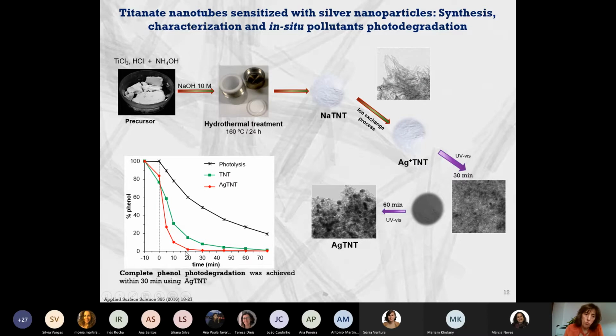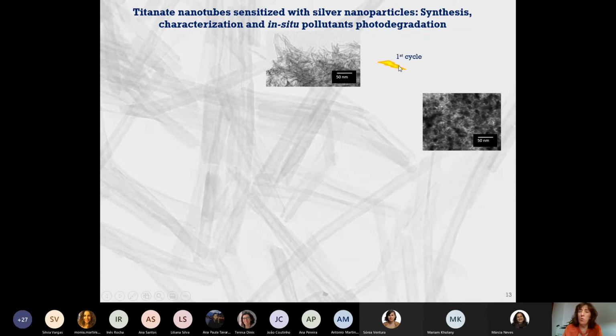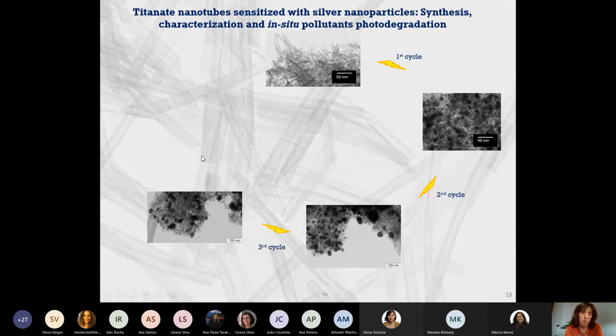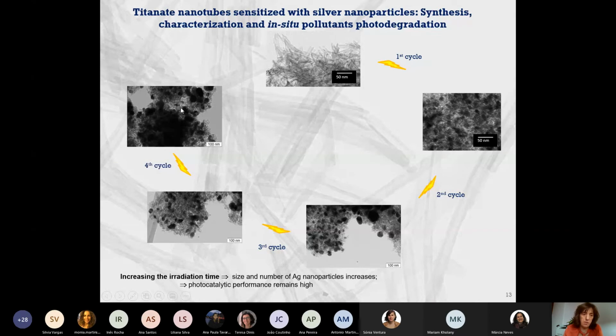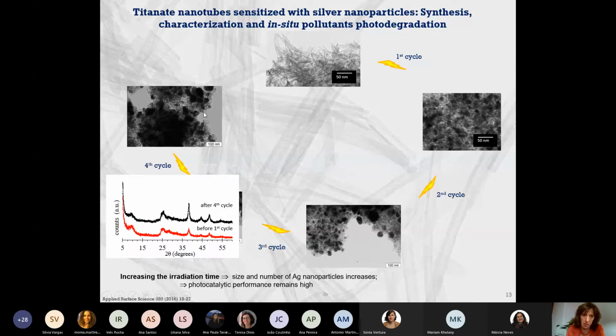So why not try to degrade phenol at the same time that we are preparing the photocatalyst? So we decide to study this point. We start with the titanates with H+, and use this sample to degrade phenol. First time, second time, third and fourth cycle. And as you can see, it seems that the amount of silver is increasing in our sample. And as you can see here, in fact, the XRD tells us that we have more crystalline silver nanoparticles after 4 cycles. And how about the phenol?